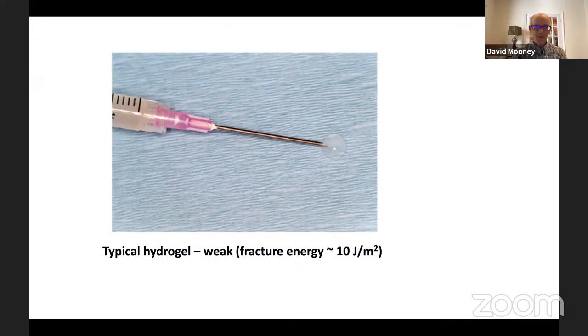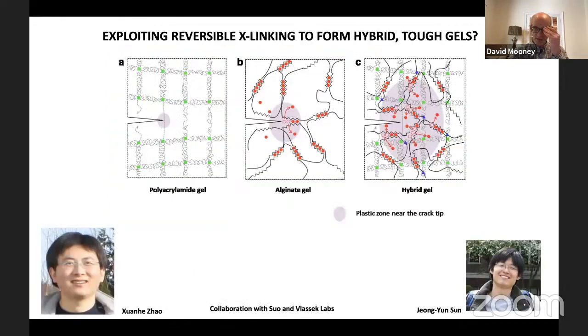One of the observations that he made of these hydrogels we were using in lots of our studies is that they're basically very weak materials, with a fracture energy of about 10 joules per meter squared. And it's not surprising for this class of materials that they'd be very weak. As he was looking at Nate Huebsch and others doing these mechanotransduction studies and beginning to recognize the importance of the mechanics of the materials, he recognized that the ability of extracellular matrix to dissipate stresses could be an important principle, not just for cell interactions, but more broadly in terms of toughening materials.